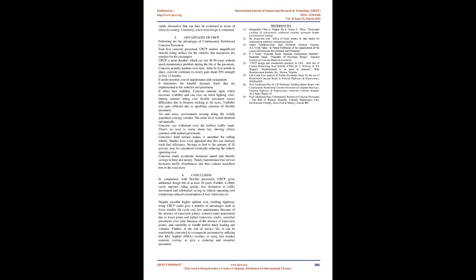Conclusion. In comparison with flexible pavement, CRCP gives additional design life of at least 10 years. Further, it offers vastly superior riding quality, less disruption to traffic movement and substantial saving in vehicle operating cost comprising reduced consumption of fuel, lubricants etc. Despite possible higher upfront cost, building highways using CRCP could give a number of advantages such as lower life cycle cost, low maintenance because of the absence of transverse joints, reduced water penetration due to fewer joints and tighter transverse cracks, smoother pavements over time, and capability to handle heavy truck loading and volumes. Further, at the end of service life, it can be conveniently converted to a composite pavement by utilizing hot mix asphalt, HMA, overlays or using thin bonded concrete overlay, to give an enduring and smoother pavement.